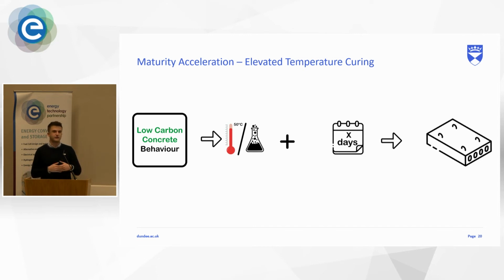Essentially, for the first 3 days, we cured it at 20 degrees to let the initial chemical reactions happen, and then we put the samples at 50 degrees Celsius for X number of days to essentially match the strength of the 90-day standard cured samples.